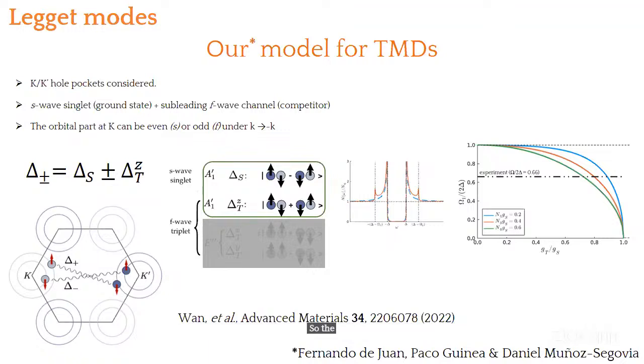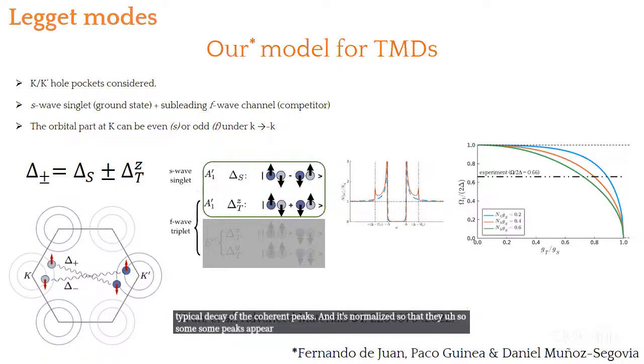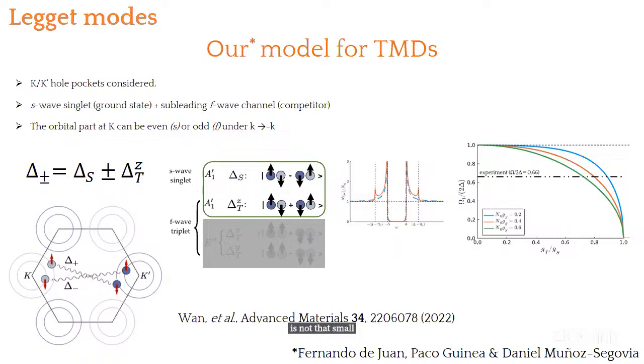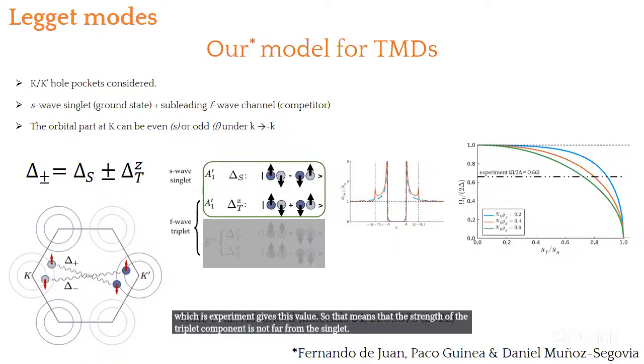So the spectral function changes from this blue curve, which is the typical decay of the coherence peaks, and it's renormalized so that some peaks appear. And actually, the strength of the triplet component is not that small, because this is the ratio between the location of the fundamental mode, normalized to the size of the gap, which experiment gives this value. So that means that the strength of the triplet component is not far from the singlet component in our case. Okay, so that's it with respect to the single niobium diselenide.